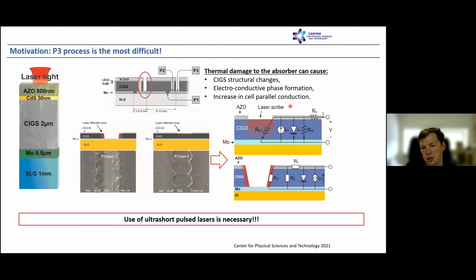This is the most challenging process, because during the laser processing you induce some heat effects, and this can lead to CIGS material degradation. That means you can have some changes in the cell electrical behavior or some additional parallel resistances due to material degradation. And of course, this will affect the device efficiency. So our primary thought was that we need to use ultra-short lasers to reduce the heat affected zones and heat effects to the minimum.